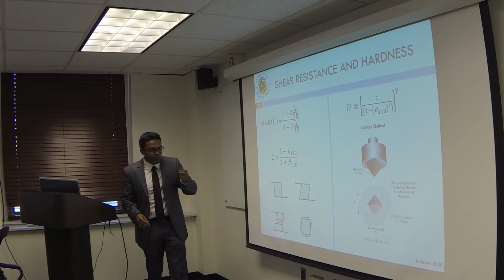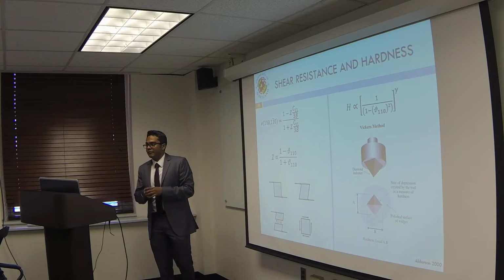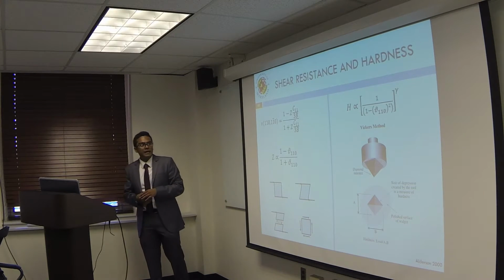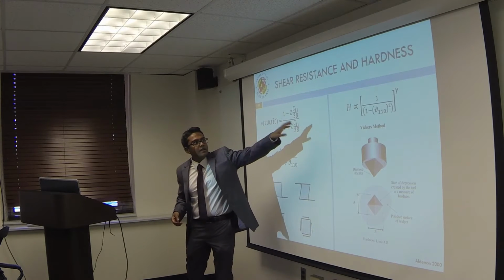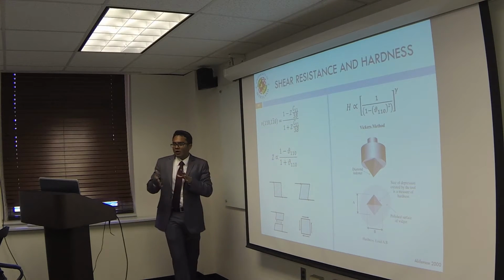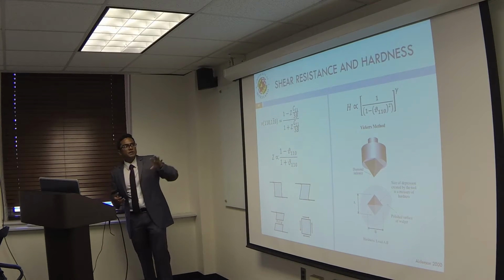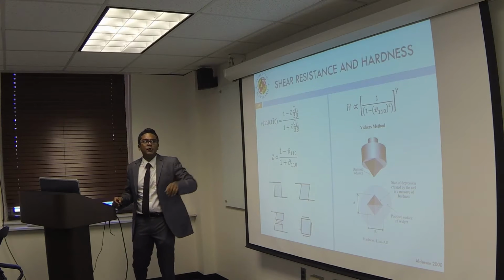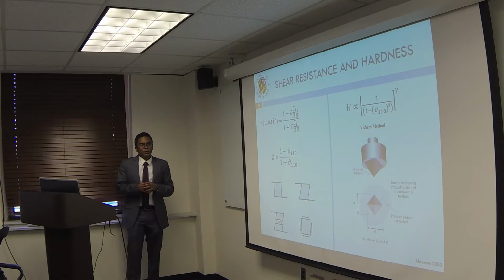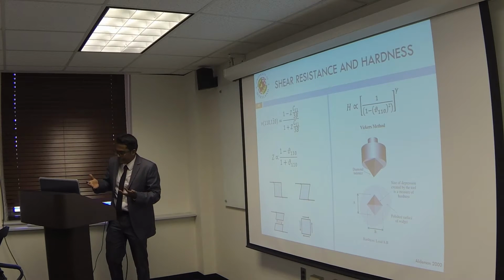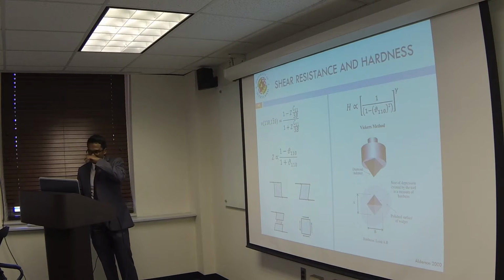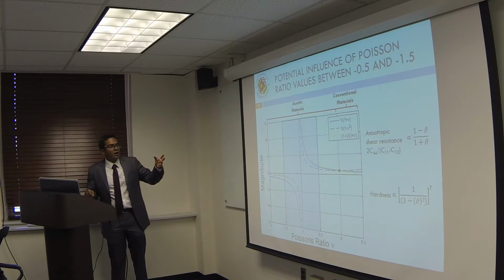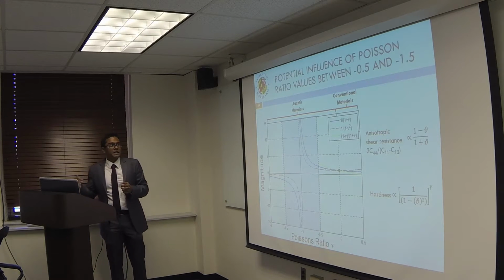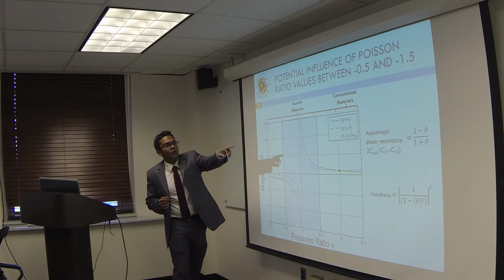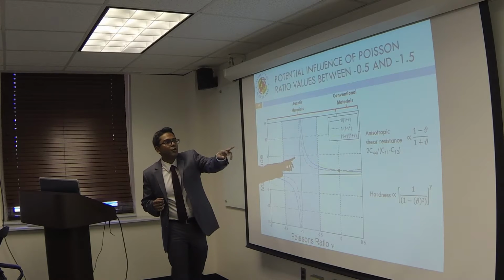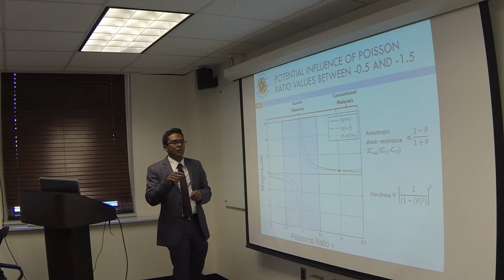And there was a previous work by Alderson, who works on auxetic foams, which is a synthetic auxetic, and he showed that the hardness value of anisotropic foams is proportional to 1 over (1 minus Poisson's ratio) squared. So in order to confirm that we indeed see an increase in the mechanical properties, we decided to do indentation testing. So if I plot the values (1 minus nu) over (1 plus nu) and 1 over (1 minus nu) squared,